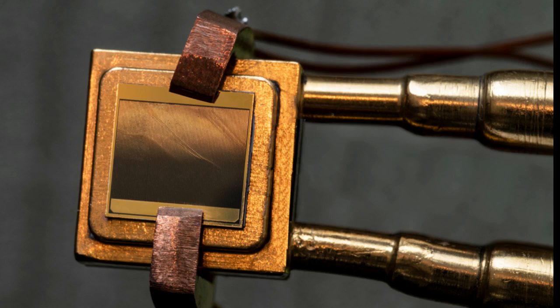The team tested the cell's efficiency by placing it over a heat flux sensor, a device that directly measures the heat absorbed from the cell. They exposed the cell to a high-temperature lamp and concentrated the light onto the cell. They then varied the bulb's intensity, or temperature, and observed how the cell's power efficiency changed with temperature.